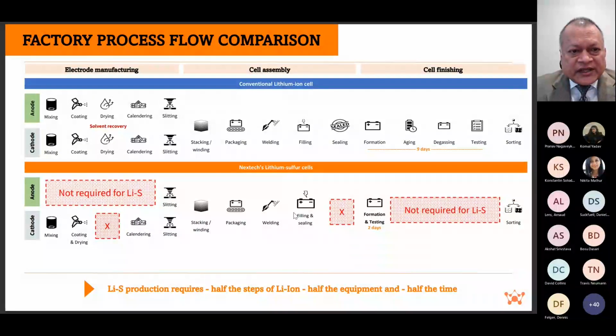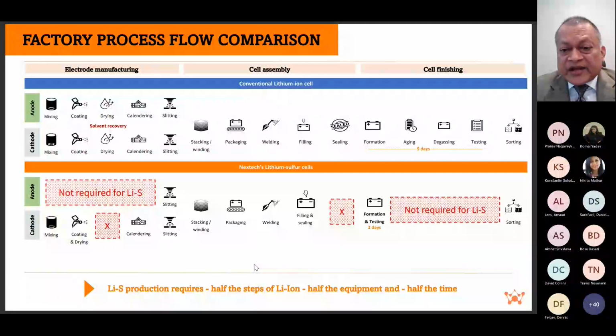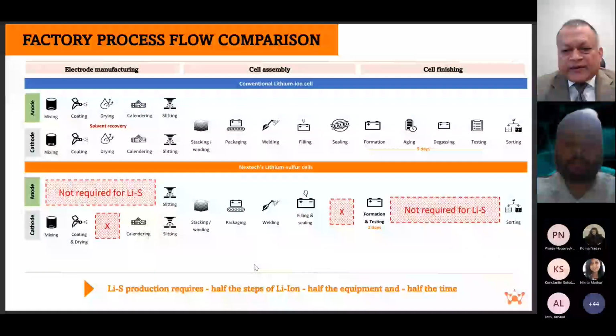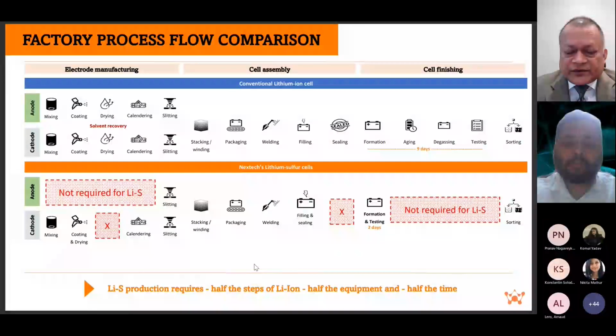And traditional electrode manufacturing, you go over 50 different steps. And compared to that, our number of steps have been brought down to less than 25, actually 22 to 23, that's what we have. And also the next thing where you save quite a bit of money is the traditional lithium-ion cells. They take anywhere between 1 to 2 weeks for formation, depending on the type of chemistry you use and type of formation cycles you deploy.